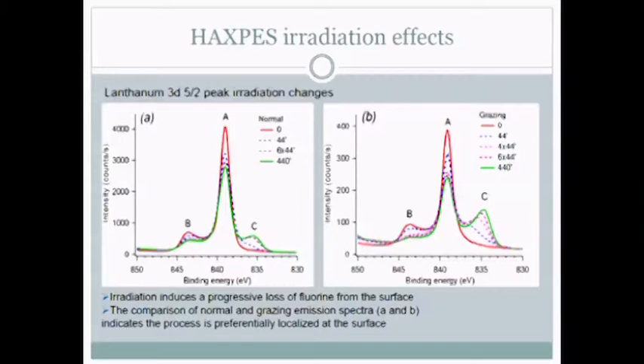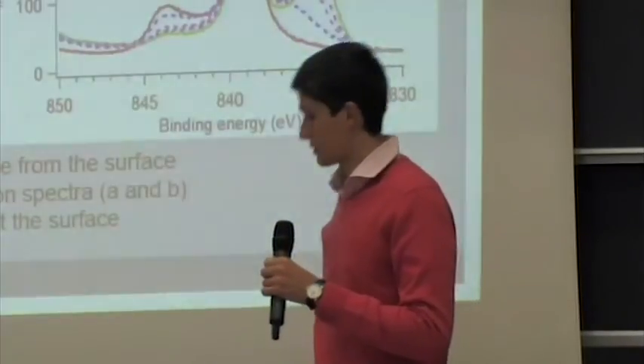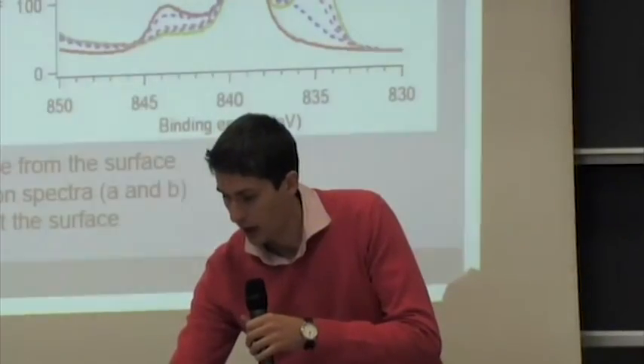And as you could see here, the C peak, which appeared and corresponds to these 3 bonds, is slowly shifting with time, which points us to progressive oxidation. So actually, it's one of the proofs of where the oxygen goes.